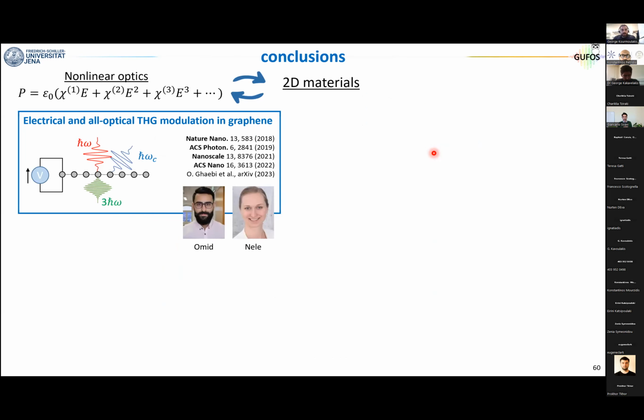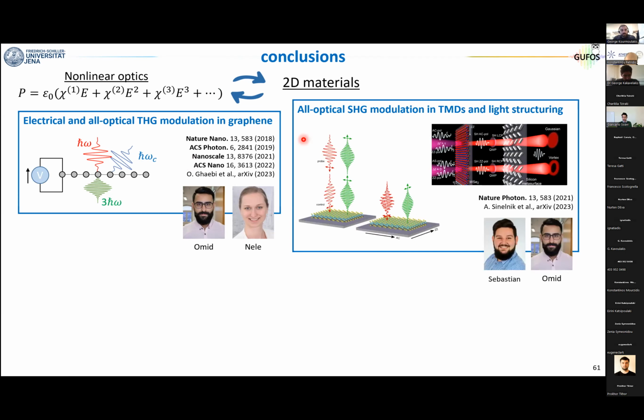To summarize very briefly, the experiments that I was showing you today: electrical and all-optical modulation of third harmonic generation in graphene. Electrical modulation because we can move across multi-photon resonances by tuning the Fermi energy. All-optical modulation because the electronic temperature has a very strong impact on the third harmonic efficiency. Then I showed you modulation of second harmonic generation in TMDs. This is based on symmetry considerations, and this is also what we use now for generation of vortex light and tuning of the orbital angular momentum.